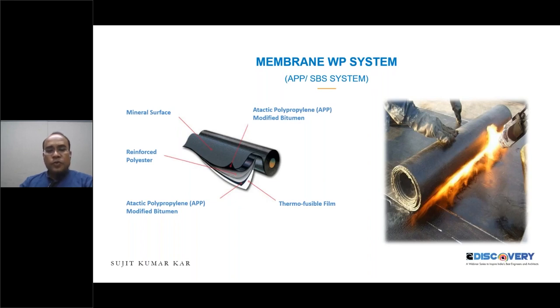And there will be the reinforcement, which should be a maximum of 120 GSM to 150 GSM. Various types of reinforcements are available for the APP system, glass fiber reinforcement or polypropylene fiber reinforcement, anything you can go for. And in the bottom part there will be a thermo-fusible film, where people use torches to burn that film, so that it will be completely stuck with the bitumen based primers. Before application, these bitumen based primers will be applied, so that it will be completely bonded.